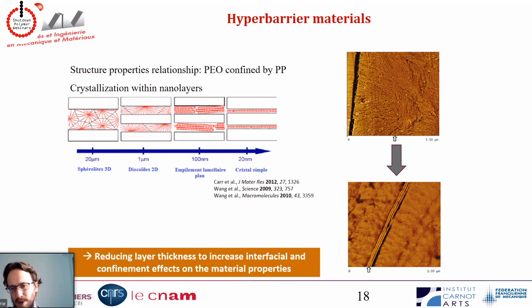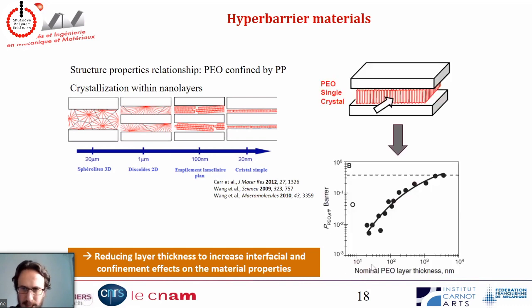So again, it's AFM measurements. You have these random lamellas, and here you have these really well-oriented lamellas that are really confined, and the size of the layer is about 50 nanometers here. So the permeability again looks like that. So reducing the layer thickness will create some interfacial and confinement effects, and this can in turn bring really new properties to the system.